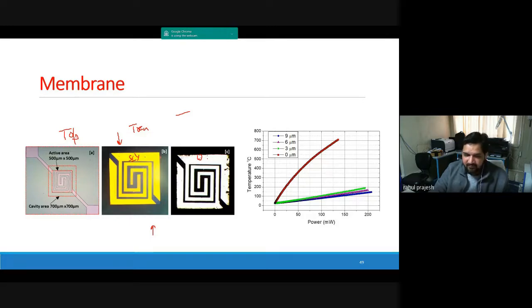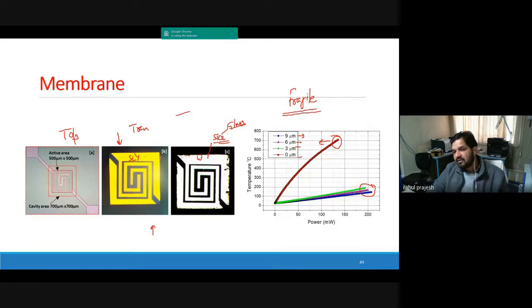But when you have no silicon left and only the SiO2 layer is there, you will get the white color, because SiO2 is glass. It's a transparent thing. So we have done some experiments. We have 9 micron silicon at the back side, then 6, 3, and 0. These are the different values we tried. When you have some silicon left, you have a temperature in the 200 degrees centigrade range. But when you have no silicon left, the temperature goes as high as 700 degrees centigrade. So that's the advantage and beauty of removing the complete silicon from the back side. Of course, it will make the device fragile, so you need to handle it with great care, but it will be very power efficient.